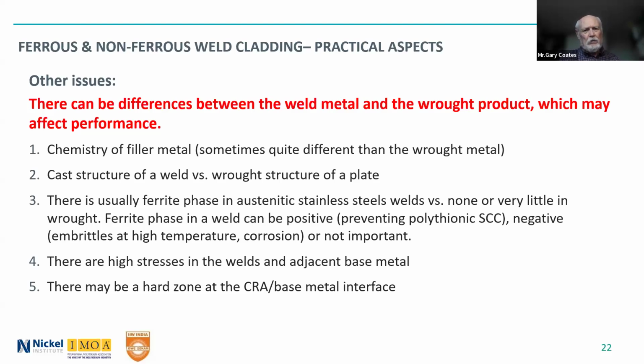You have a cast structure of a weld versus the wrought structure of a plate. Of course, same thing is true if you're welding two plates together. You have the weld and the wrought structure of the plate, but you have the weld that is the cast structure. Again, a few cases where that is significant. In austenitic stainless steels, you have a ferrite phase there, which is not present in the wrought material. And sometimes ferrite phase can be positive. One example is preventing polythionic stress corrosion cracking, which happens in the oil and gas industry a lot. So ferrite can be a benefit there over wrought material.